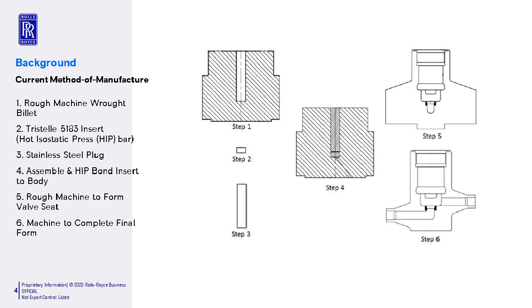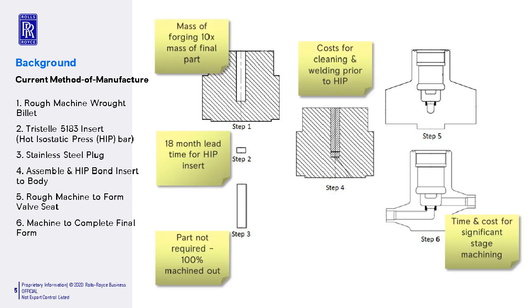So what are the issues with this method of manufacture? Well, so the mass of the initial forging is around 10 times that of the final part, so we have a significant amount of material waste. In step 2, there's a long lead time in terms of production of the hip insert. And step 3, the stainless steel plug is not actually part of the final component and therefore is 100% machined away. There's a cost in terms of cleaning and welding of the parts prior to the hipping process. And then, as mentioned, there's a significant time and cost for the actual machining stage and producing the final part from the billet.